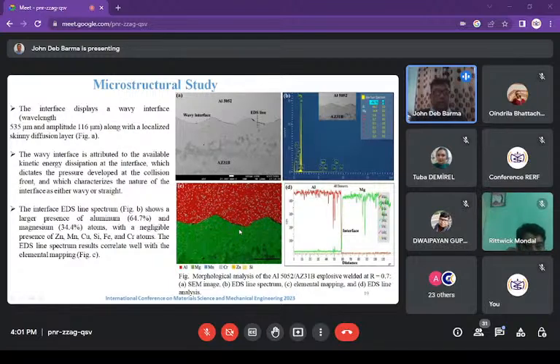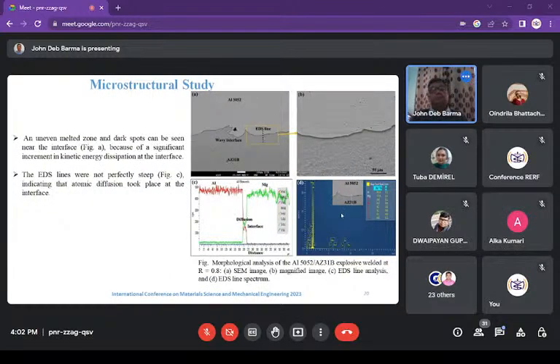And if we look at figure D, the EDS line investigation across the interface shows steep, here you can see this one, it shows steep element dispersion lines, which indicates the formation of locally thin diffusion layers. Now this is the morphological analysis of the weldment which is done at the loading ratio of 0.8.